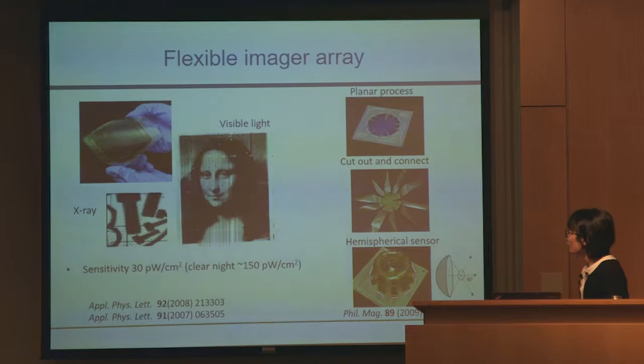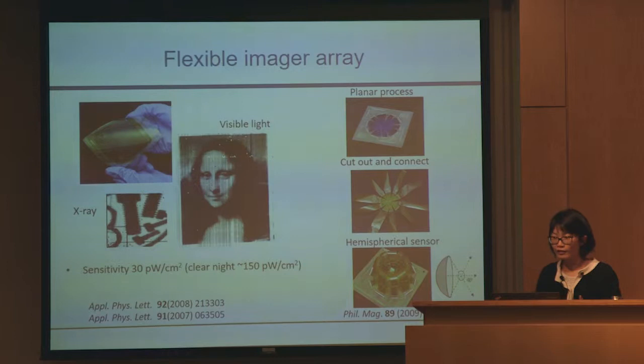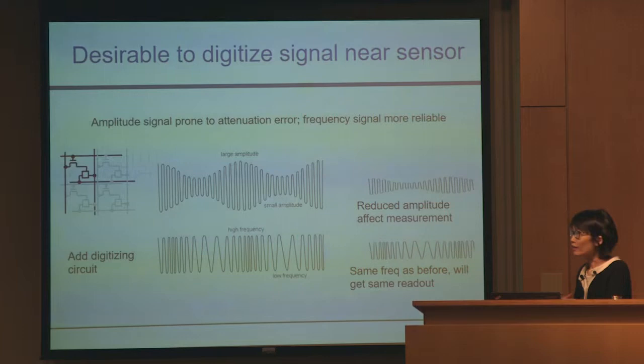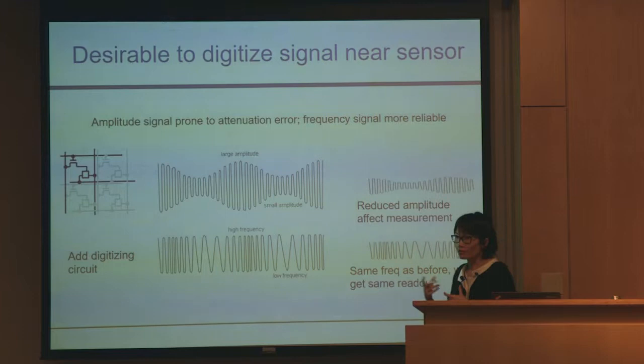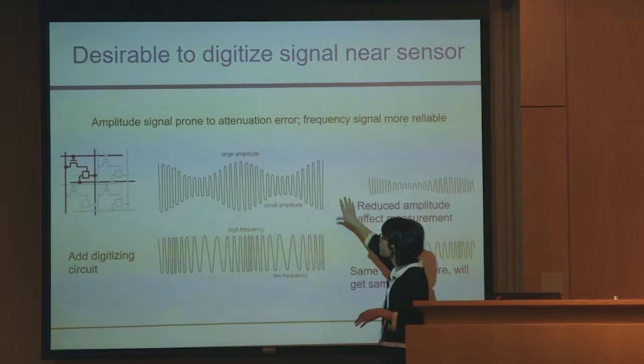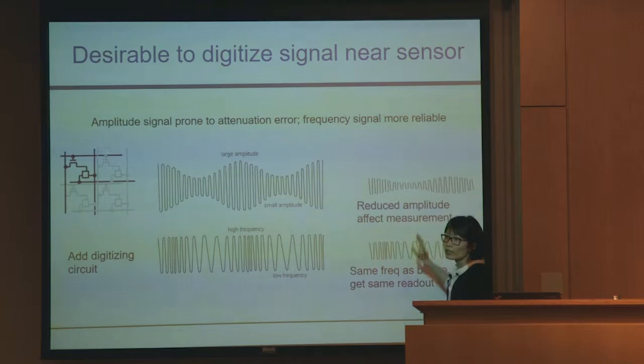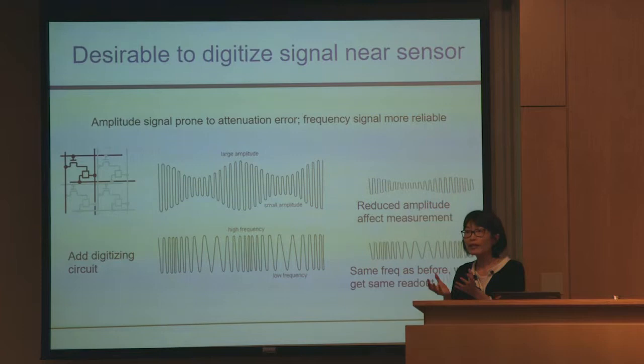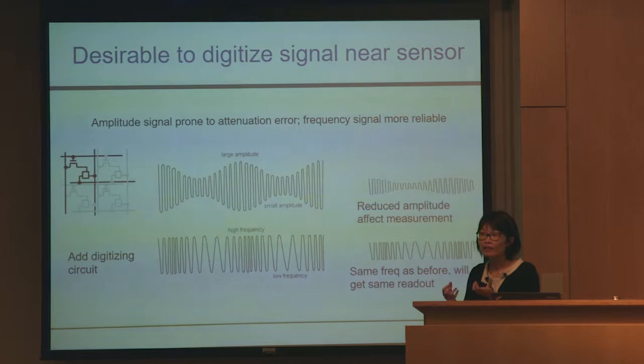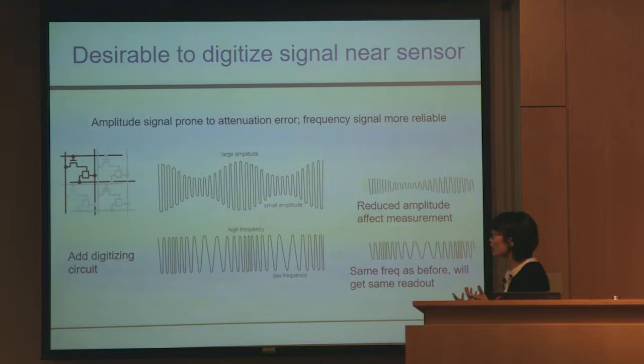And so when we start to do this type of mechanical assembly, we start to wonder, well, if we subject the material under stress, what will happen? Will we get degradation in performance? And indeed, we do. So for example, in one area of the substrate, we might see higher resistance than in another area. And so now, if we have more resistance, you can imagine the signal coming out from it would be attenuated, right? And we could calibrate this if it's a fixed structure. But then if people use it arbitrarily and bend it at different angles, then we cannot even calibrate out that attenuation. So now we have to find another approach that we could account for the mechanical problem.